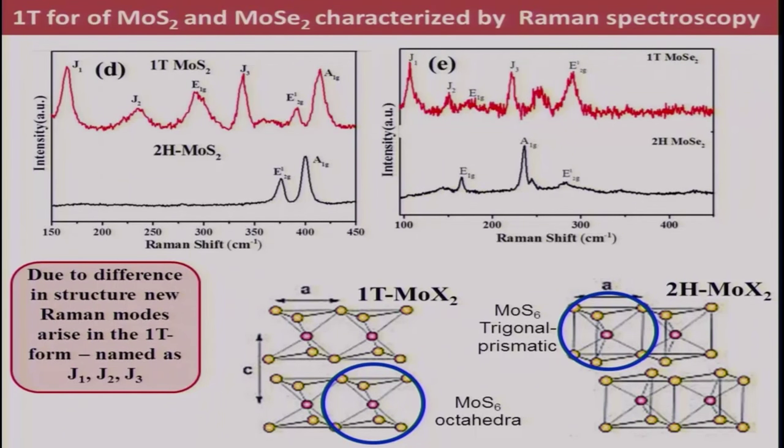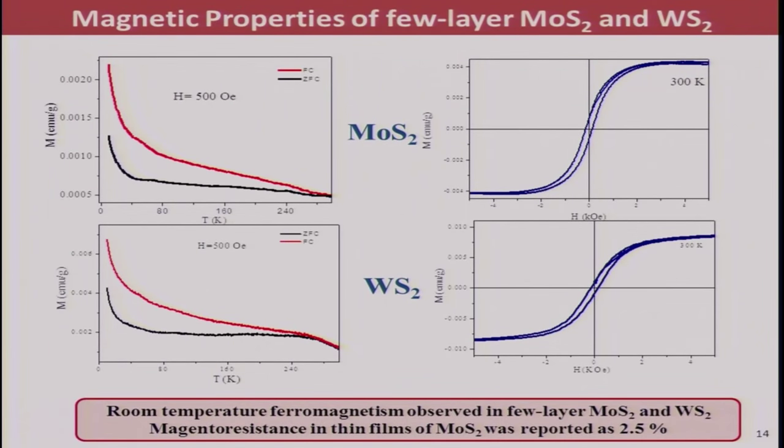In fact, soon I'll come back to this problem again of using 1T MoS2 for some applications. It has very, very interesting properties. Unfortunately, 1T MoS2 is a bit unstable. As you make it and keep it, you can see it slowly transforming to 2H MoS2, quite often also giving another polytype, 1T prime MoS2, as well. But MoS2 has many properties. I'll quickly go through in a few minutes some of the properties which are well known.